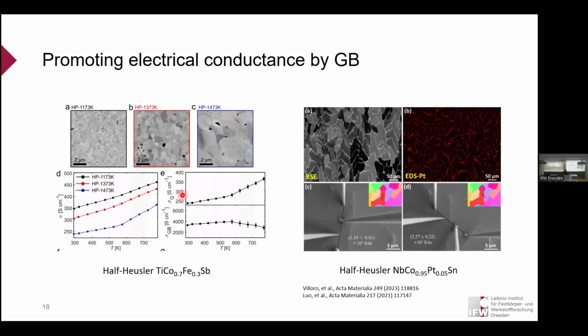Similarly, people have also been trying another material, also a half-Heusler, niobium cobalt tin. People do platinum doping at the cobalt site, 5%. And they found that with this doping process, platinum does not really enter the lattice, but instead it segregates at the grain boundaries. And you can see from the mapping, this platinum follows these grain boundaries. And then these people have this technology to do local probing of the conductance. So what was found is that if you measure the local resistance across a grain boundary, the conductivity is actually higher than when you do similar measurements in the grain interior. So that means the grain boundary itself is not only a source of charge carrier scattering, but could also be a transport path that can promote overall conductance of this material.